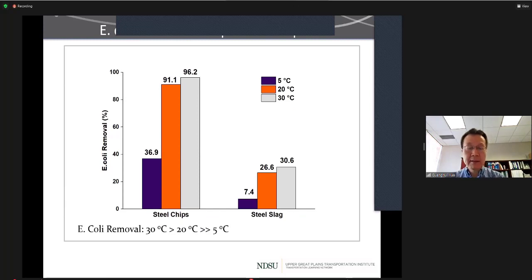And for temperature impact, based on our results for steel chips and steel slag, we learned that for 20 degrees C and 30 degrees C, the difference is minor, and we were able to maintain good removal for the two temperatures. However, when the temperature dropped to 5 degrees C, the removal efficiency substantially reduced. So we expect that during early spring runoff, when the stormwater runoff temperature is close to the freezing point, the removal efficiency will be reduced. This is likely because the mobility of E. coli under low temperatures will become much less compared to normal stormwater runoff temperatures.